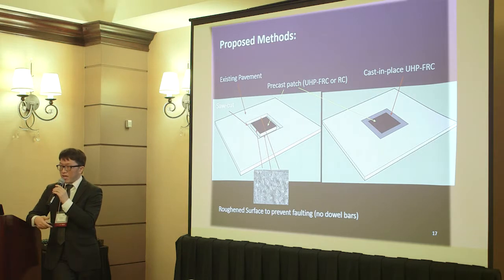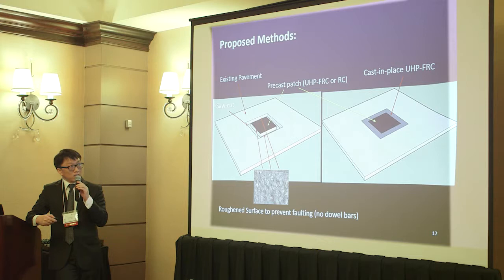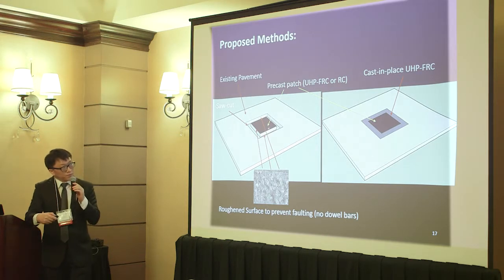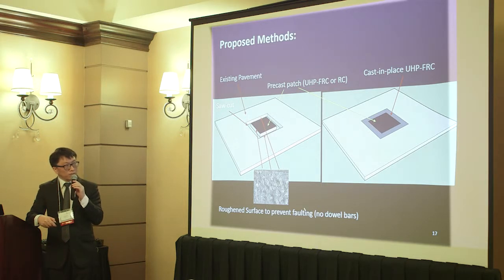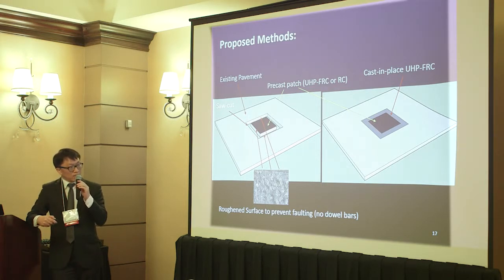If this region is under very high stress or critical, we use UHP-FRC as a high performance material, or RC or PC with HPC, for example. So this patch, including this saw-cut region, will have its surface roughened, and no dowel bars used. This roughened surface will provide very high shear resistance to prevent faulting between the existing concrete and the new one.